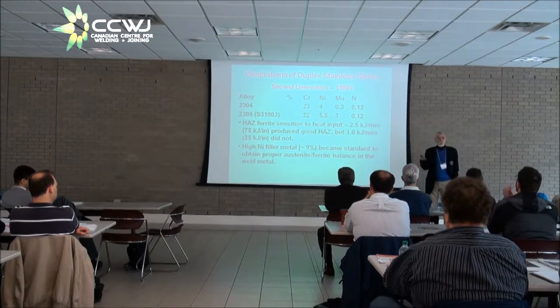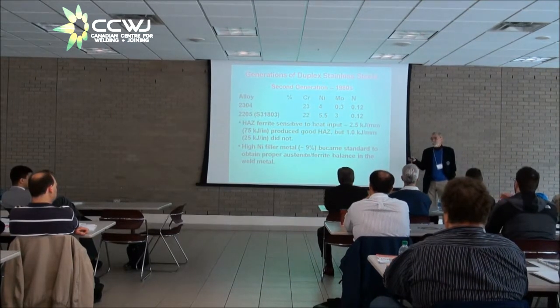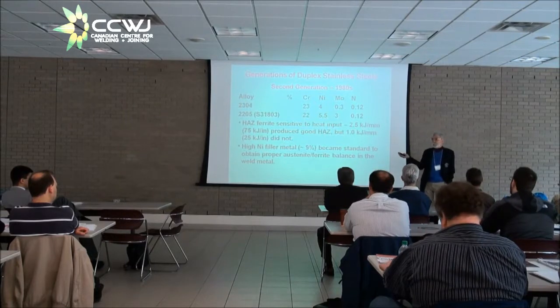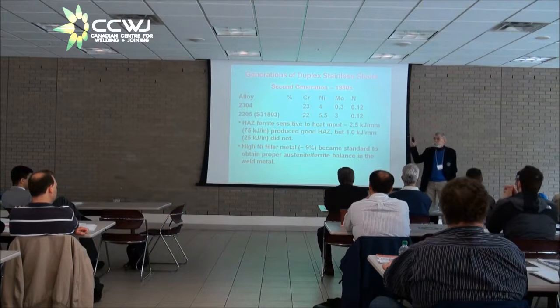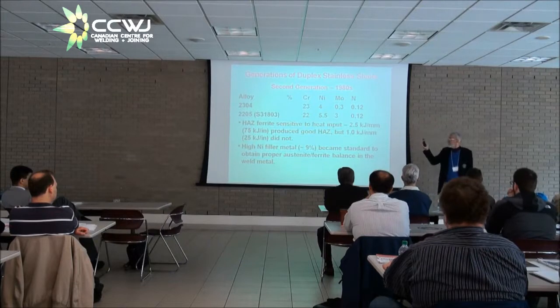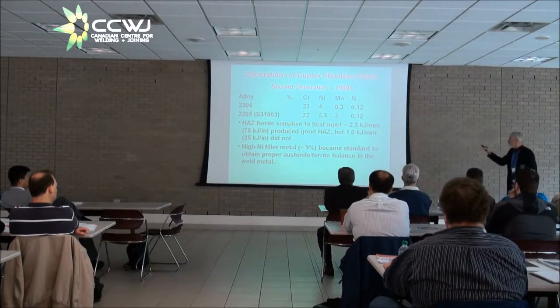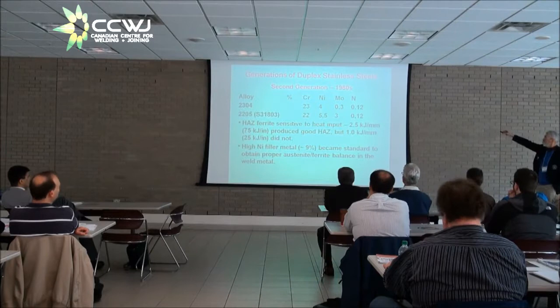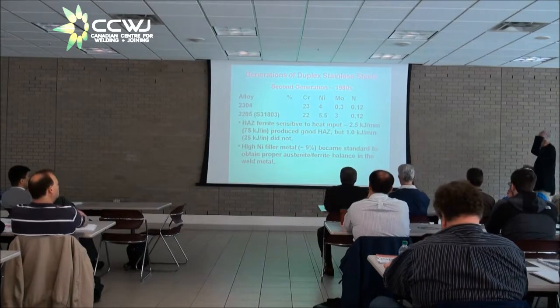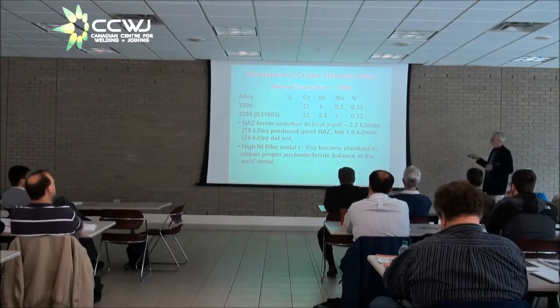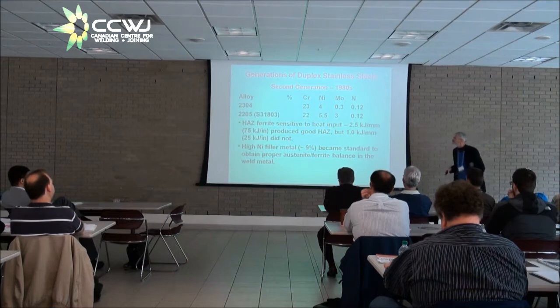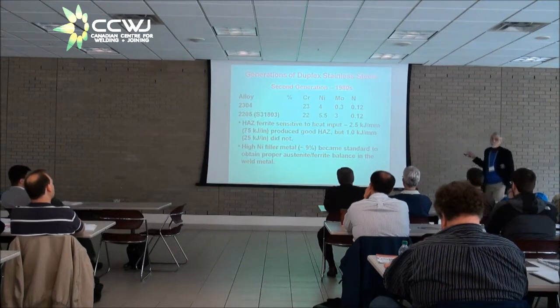And air is 80% nitrogen. So they accidentally got nitrogen into the metal. And voila, the weldability improved markedly. So in the second generation of duplex stainless steels, the ones that proliferated in the 1980s, typified by 2304 and 2205, those materials had about 12 points of nitrogen in them.